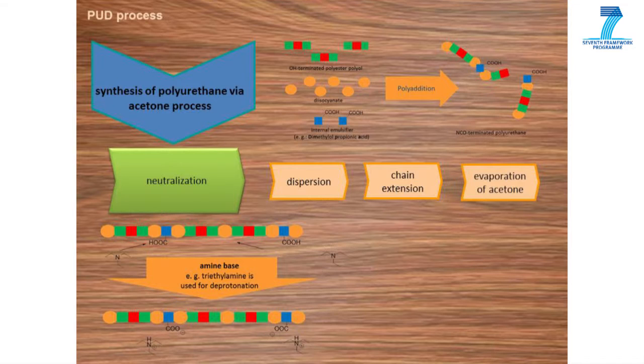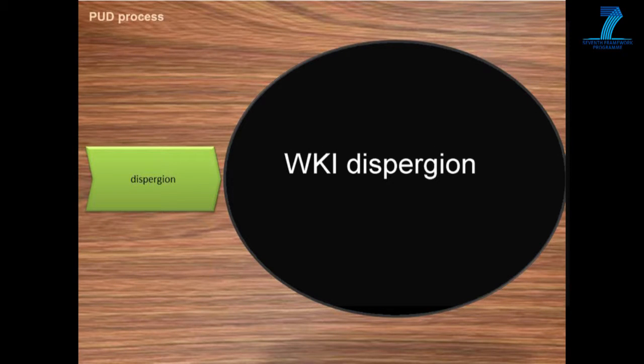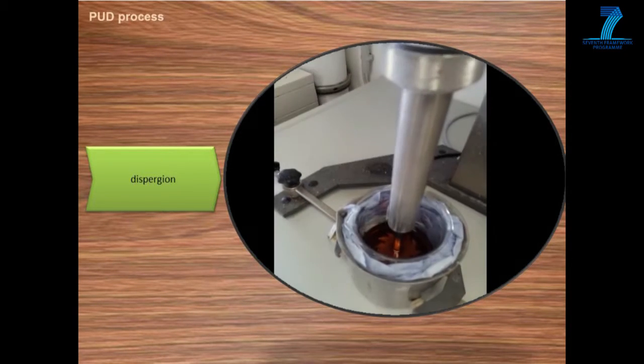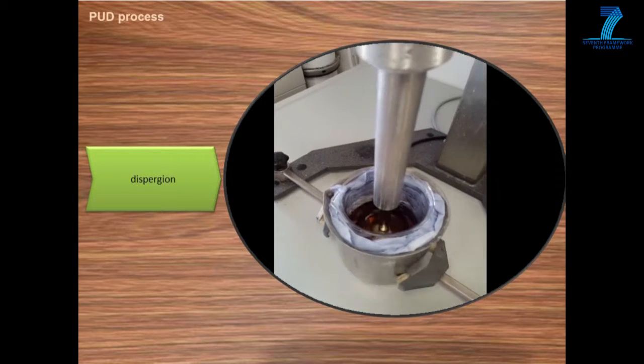Polyester polyol and DMPA react with diisocyanate to form polyurethane. The isocyanate is used in excess, giving NCO terminated polyurethane. Ratio of NCO to OH groups allows to adapt the molecular weight of the polyurethane. With the neutralization process, the ionized polyurethane can now be dispersed in water.